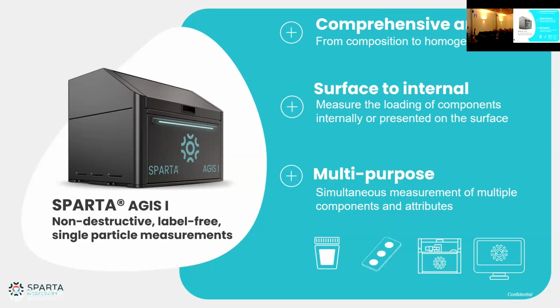But if you added some targeting ligand free in solution that wasn't bound to your particles, it would just show that there was no targeting ligand. So it's not getting confused by stuff in solution, but it can separate those two signals out; you see anything that is linked to your particles. If something leaches out, you can see the decrease on the particle. We've done studies like that before with drugs leaching out of the particles, and we can see the decrease. The advantage is that you don't need to deeply purify your sample before measuring, because we are not looking at what's free in solution until it's at high concentration.